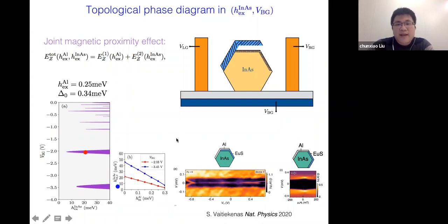So this may explain why the zero bias conductance peak is only observed in the overlapping geometry and not in the non-overlapping geometry. If we assume that we can approximately model this non-overlapping geometry by just turning off the exchange coupling inside aluminum, because there's no more overlap between aluminum and europium sulfide, there's no proximity effect between the two.